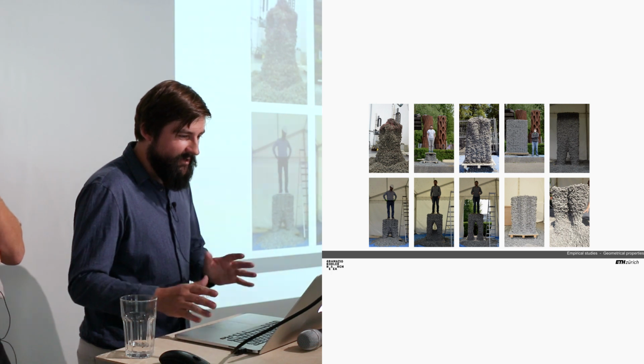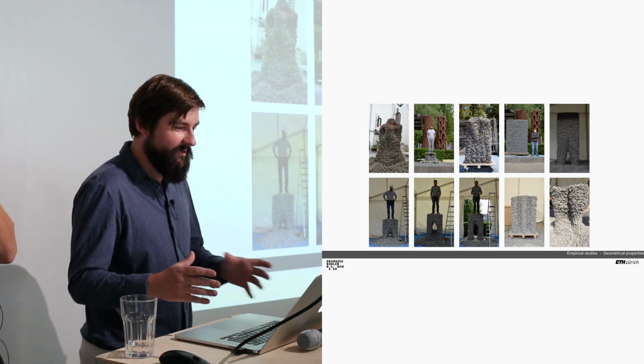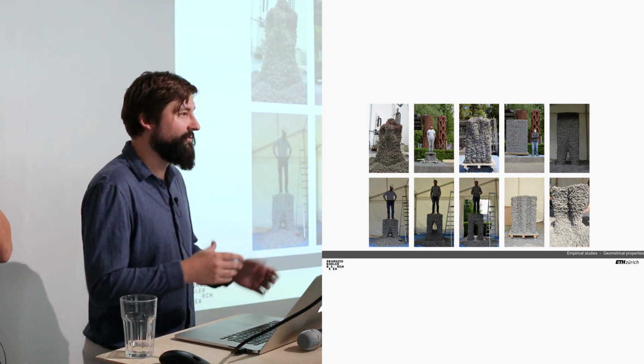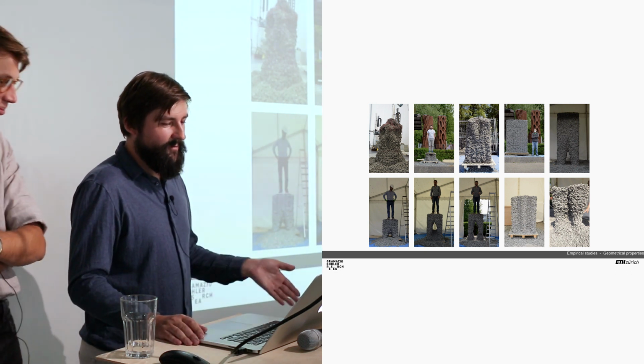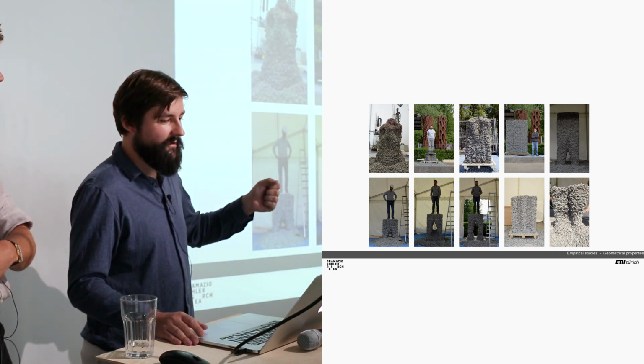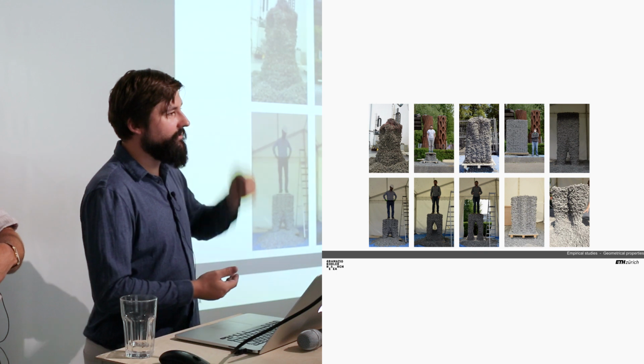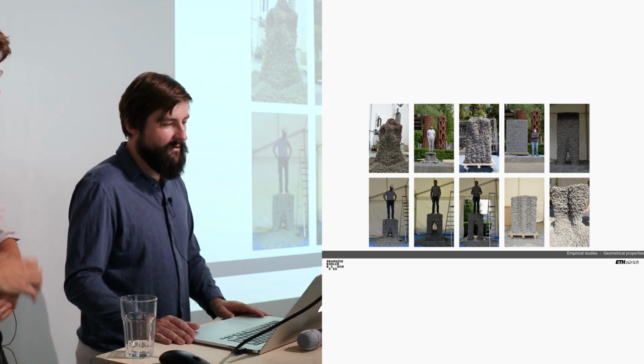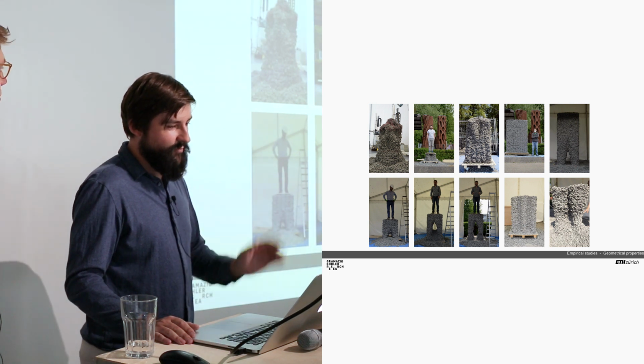So to be a little bit more on the safe side, we actually just decided to do a rectangular volume, because if that doesn't work, then we're really in trouble. And that's when we also introduced packing. So every 5 layers of fabrication, we would condense the material a little bit by jamming it. With the concrete compactor. Exactly. And that then worked perfectly well.